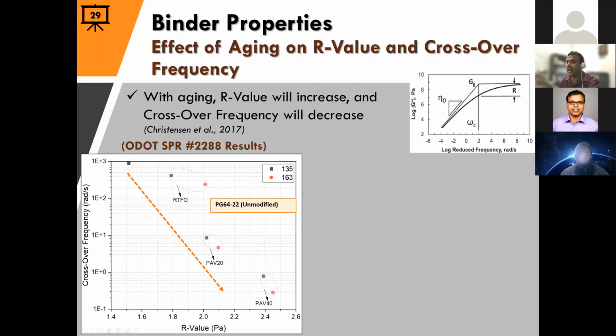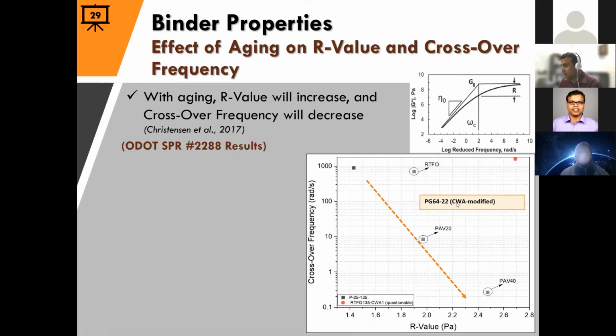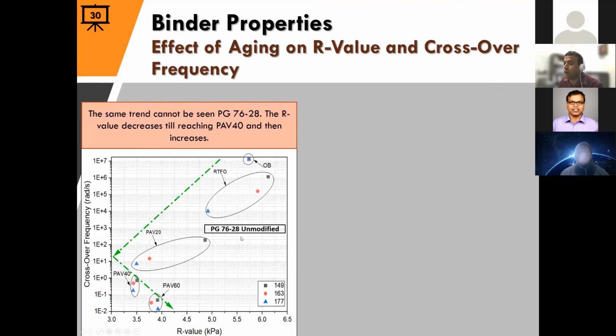This is another way of analyzing for R value, which is proposed by Christensen. And it said that with aging, the R value should increase, and the crossover frequency, which is where the G prime and G double prime lines cross, which is 45-degree phase angle, will decrease. And for unmodified 64-22, we see that trend. For modified, which is chemical additive modified, we see the same trend. But when we go to a very highly polymer modified material, that trend is not visible.